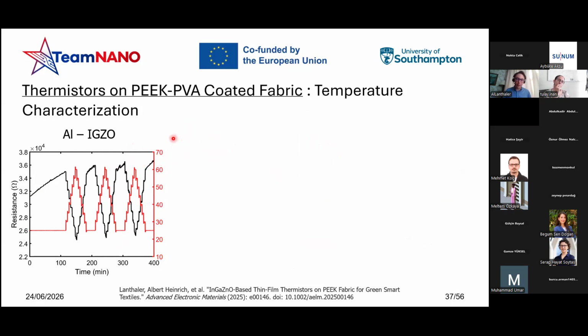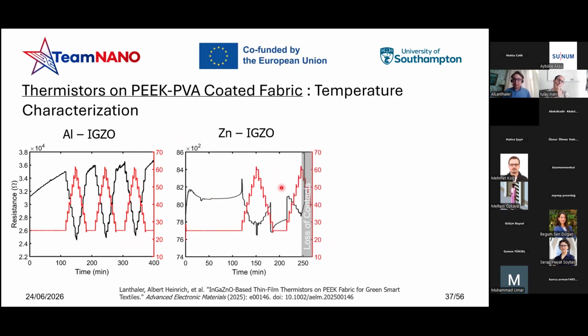It was reliable, but not precise nor accurate, because as you can see here, it's not achieving exactly the same temperature step as before, and this, of course, affected the calibration of the device itself. For the zinc oxide, unfortunately, we encountered a loss of contacts during the second cycle for the majority of them, but we can actually still calibrate the sensor throughout the first temperature cycle.